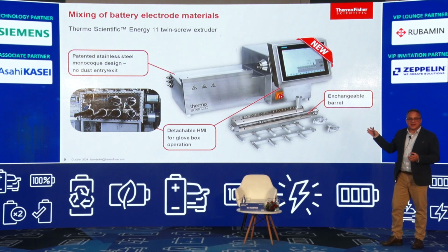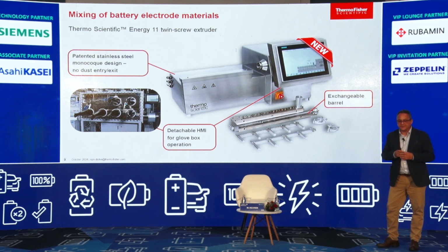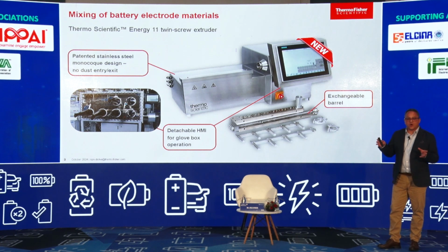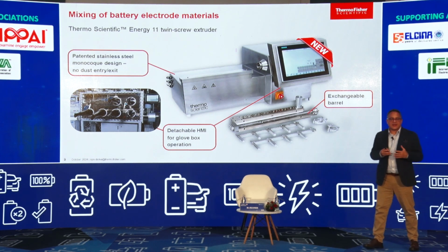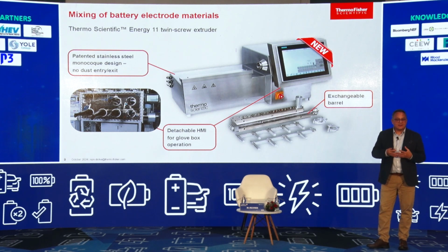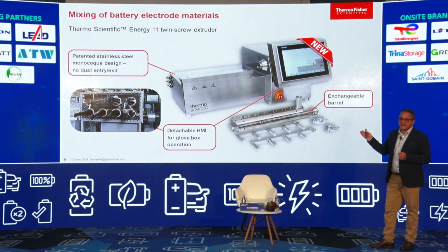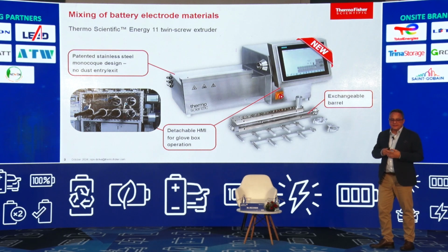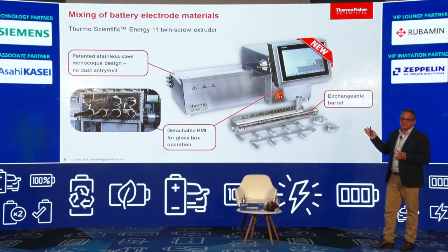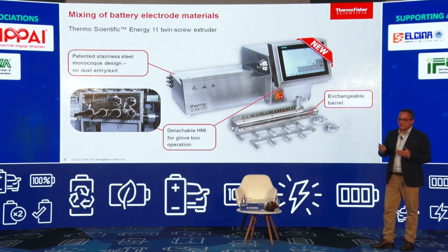So this is our new Energy 11. It launched around 10 months ago. It's a very small format mixing technology. It fits on a benchtop. It fits in a fume hood, but has the capabilities of mixing up to around 200 liters equivalent. It's a continuous process mixing capability with very high shear forces. It's designed to be adaptable and work in glove box environments so that you can create mixes and compositions very quickly and with very high dispersion.